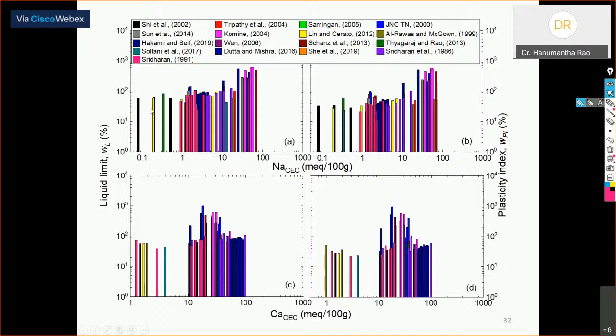You can see in all previous correlations there was an increment reaching a peak and then a decrement. But when we correlate the liquid limit with NaCEC, there is a continuous increment of the liquid limit, and thereafter it became saturated, but there was no decrease. Similarly, even for plasticity index, there was a continuous increment of the liquid limit or plasticity index, and then it reached a peak value.